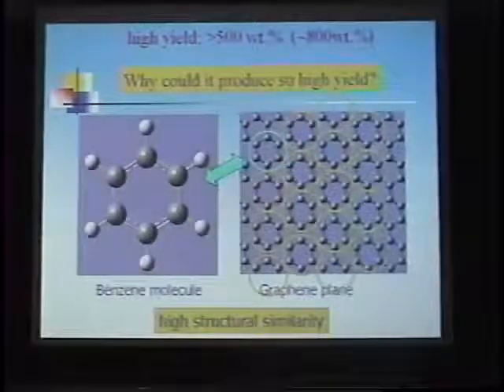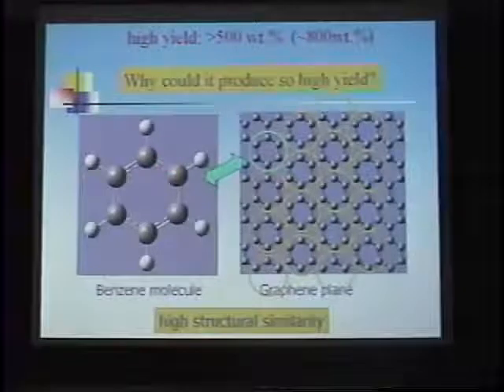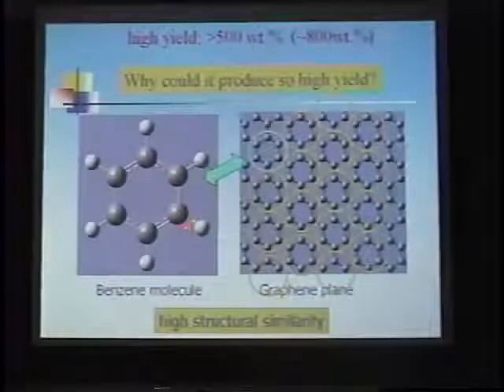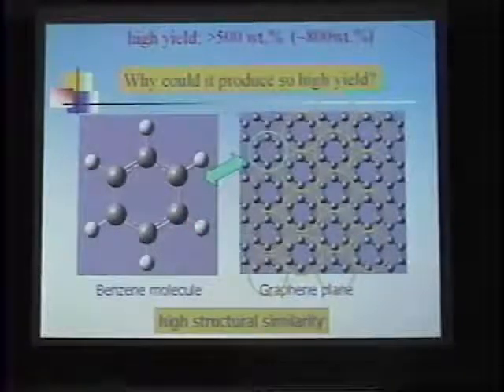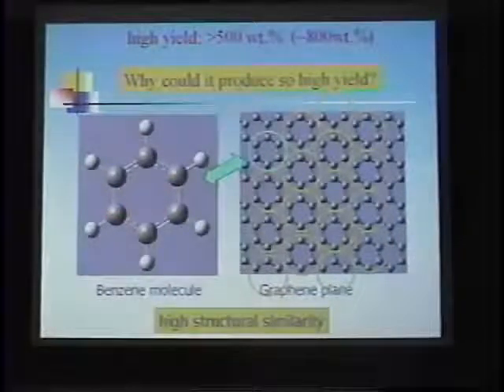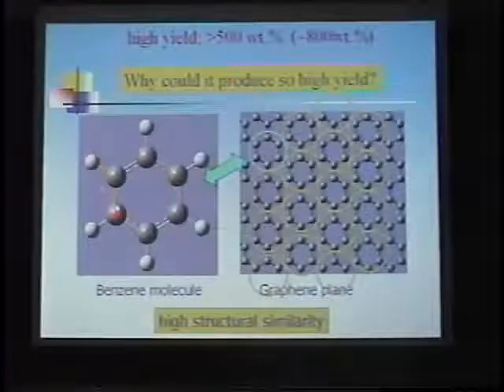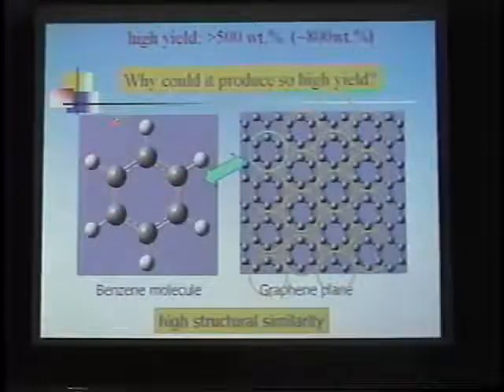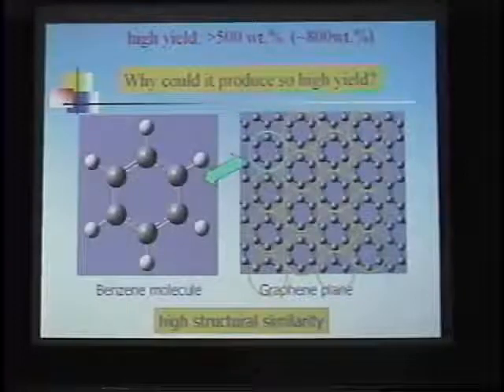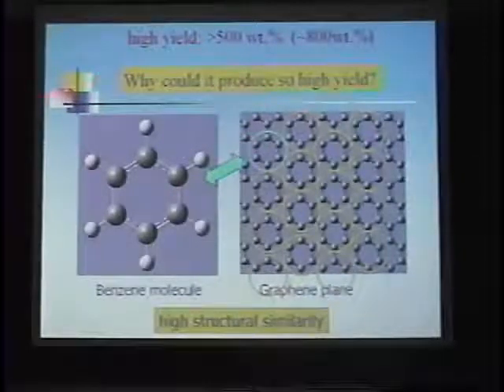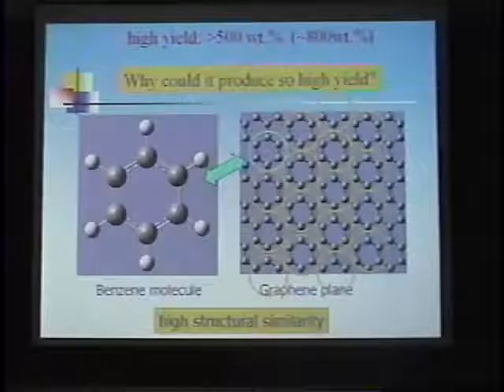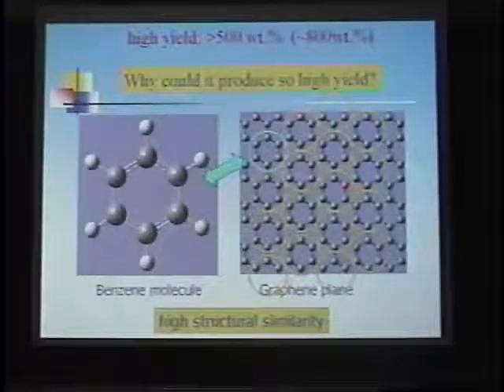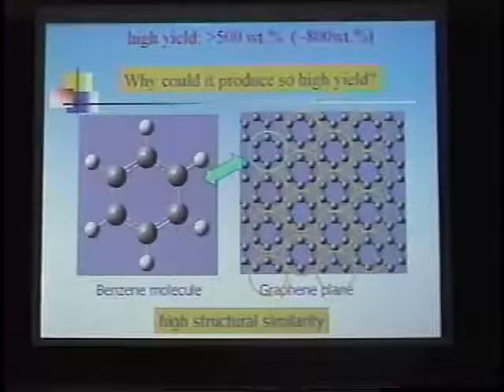So if we could find a suitable catalyst to preferentially dissociate these carbon-hydrogen bonds, then it's possible to construct carbon nanotubes with the carbon-6 ring as the building unit. If the carbon-6 ring is the building unit, then the yield will be much higher, since usually carbon nanotubes are constructed atom by atom, and this is by 6 atoms at a time.